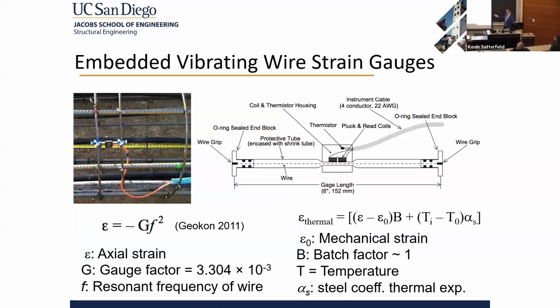One tricky thing with these is that temperature causes... they work like a guitar string. So you have a magnet that plucks the string. When you heat it, that string actually expands. So if you don't process the data correctly, it makes it look like your pile is contracting, even though it's expanding. But if you do these thermal corrections properly, you can see that the pile is indeed expanding.